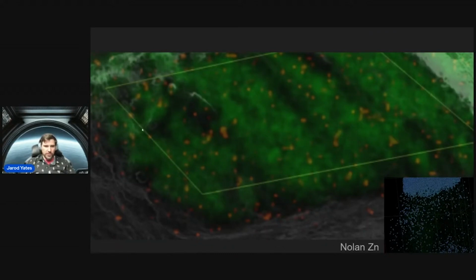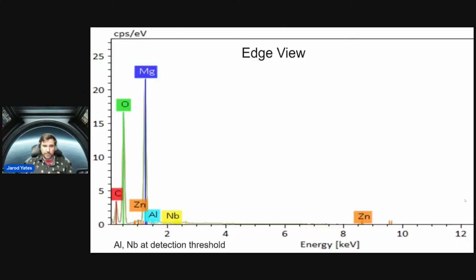So for reference, here are those little cylinders that have some connecting lines going between them. This green is the oxidation that is going on at the surface. And you can kind of see how we got some lines of zinc, some semi-regular patterns of the zinc. The reason why I say that's important is this picture down here is from Gary Nolan's YouTube video that I just referenced. In their samples, he was noting how some of these atoms in their materials seem to have very specific atomic placements. So it's important to keep in mind that we have potentially atomic placements of certain elements going on in this sample as well.